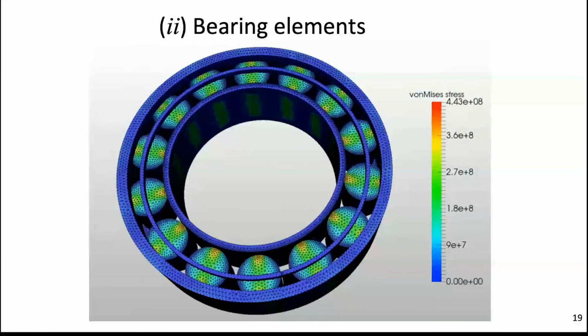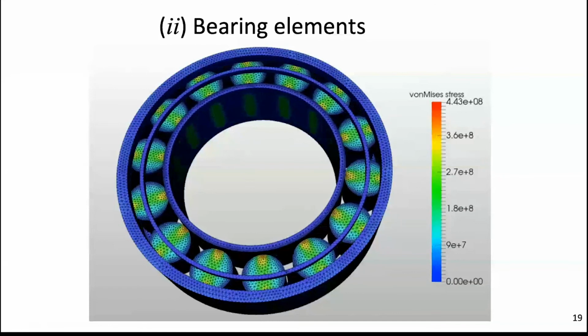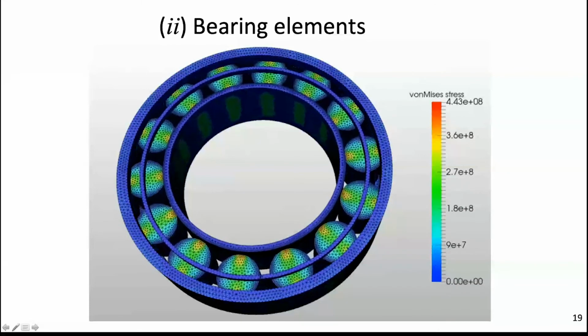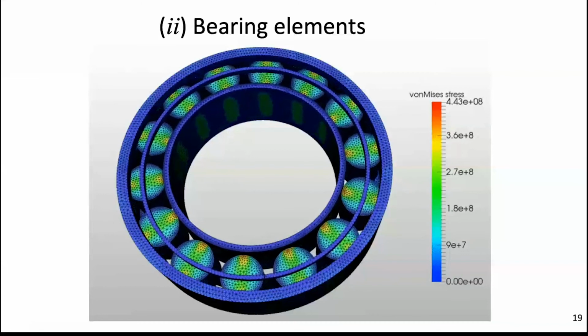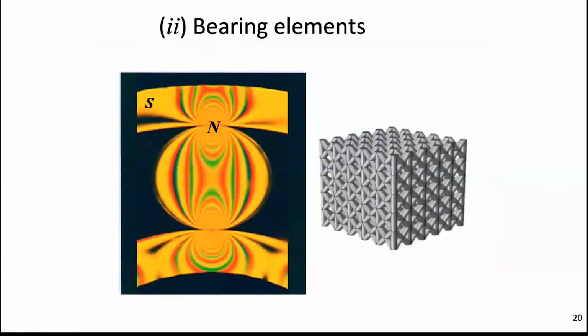And you can think to yourselves, what a waste of material this is, because I have properties at the center that I don't need. Essentially, I could save material if I made the center of a different nature. So what I'm proposing is that you create a more hollow core part of the roller, this lattice type of structure, whereas the contact surface is a nanostructured material. Why nanostructure? Because the nanostructured metal gives me ultra hardness and great wear properties, or is resistant against wear. I can also produce this solid solution at the outer and inner bearing rings.